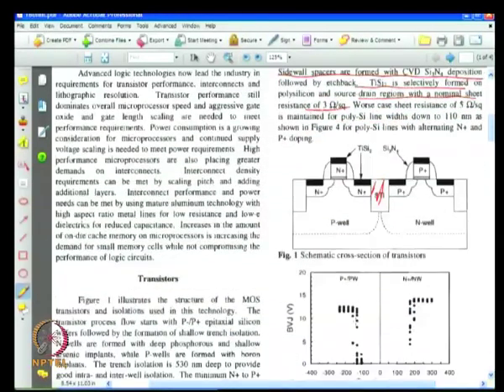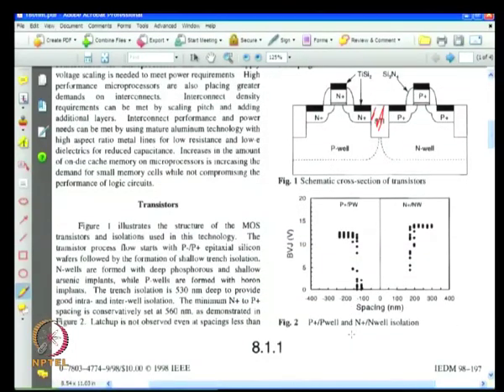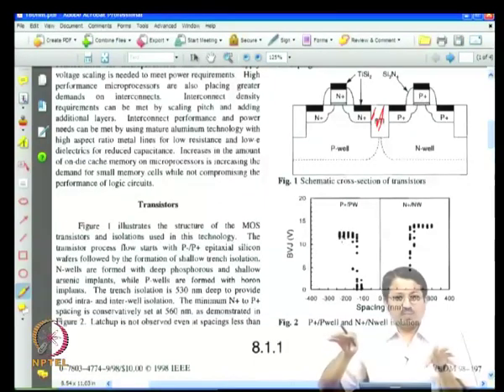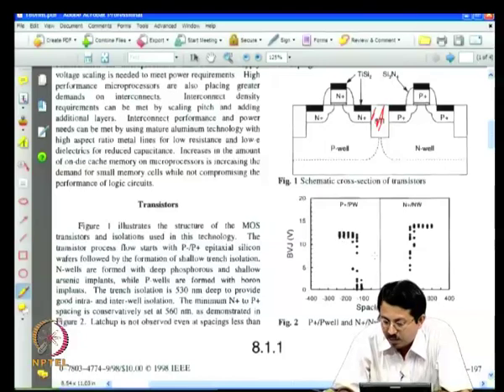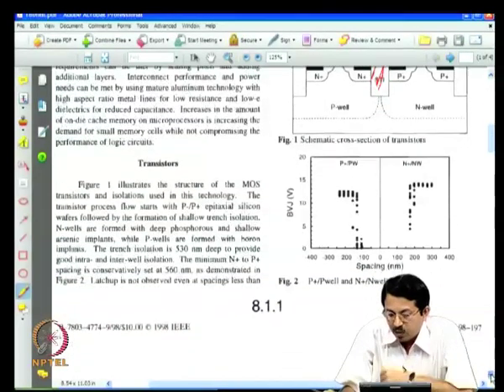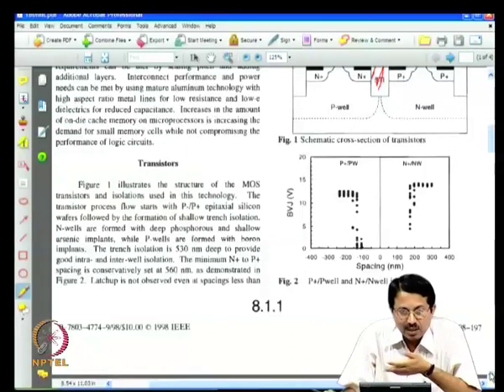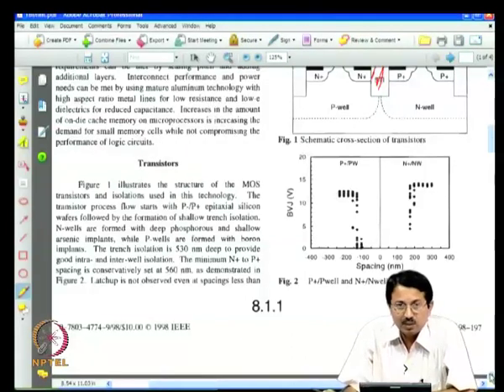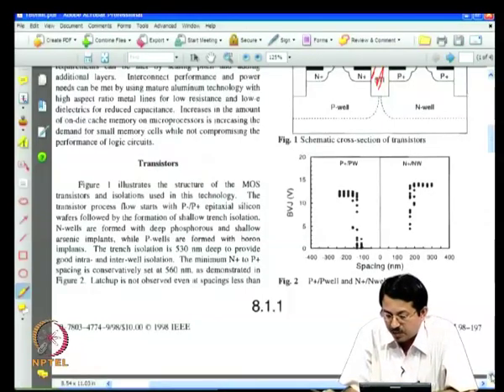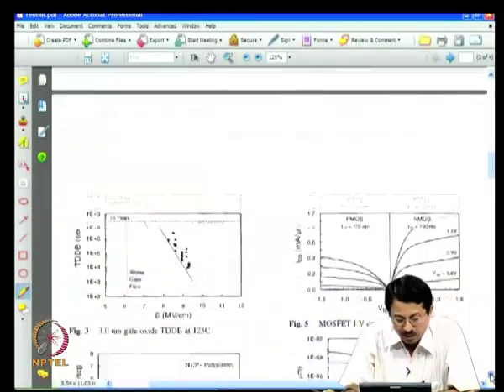So this is how you would define the transistor, and then you will have to characterize a lot of things. You will have to make sure that the isolation is sufficient. For that you need to characterize the breakdown voltage, that is between this and this. If you apply 2 volt, it should not break down, the breakdown voltage should be more like 5-10 volt. So for all practical purposes these two are perfectly isolated. They are essentially demonstrating all these characteristics. You can go back and go through these papers. These papers are certainly available if you are an IEEE member, or if your institute is subscribing to IEEE journals, you will certainly have this listed in the IEEE publication.